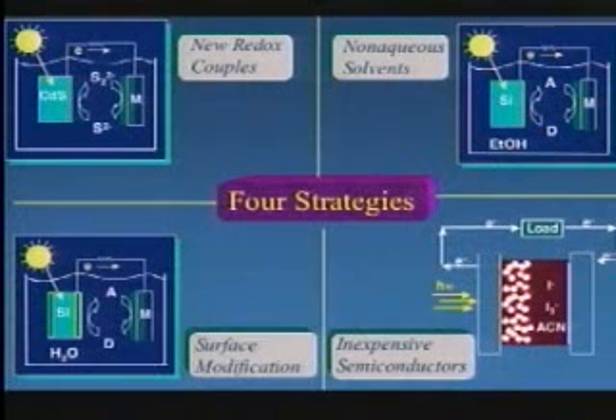What we're doing with this is because these are not insulating, but because we can use the conducting organic principles of conducting organic polymers, we actually are exploring now whether or not we can terminate the surface and, unlike oxide, have a resonant bridge between one particle and the other, where the idea is that we're going to make the electrons hop from particle to particle and not the holes. And then in a separate process, make the holes hop from particle to particle, not the electrons. And you can see what would happen if you could do that. You would basically have made binder and pigment, and you've made paint. Where one side is the N-type paint and the other side is the P-type paint.